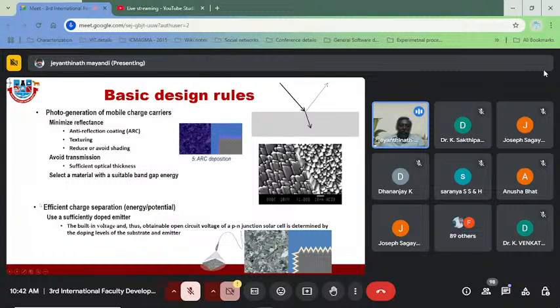The next point: once the photon is captured effectively, you are generating electron hole pairs, and once the electron hole pairs are generated, you need to have a separation of these charges. To do that, you need sufficient doping in the emitter. So the built-in voltage has to be produced, and the obtainable open circuit voltage of a PN junction solar cell is determined by the doping levels of the substrate and the emitter. So that is the main reason why we make PN junctions.